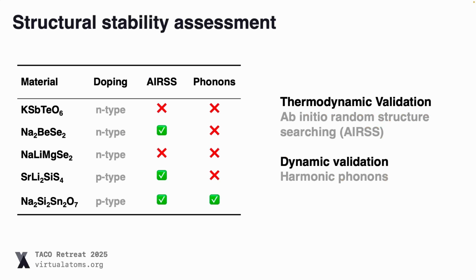So we wanted to understand finally whether these materials that have been proposed were actually stable. And so what we did is we essentially did ab initio random structure searching from scratch to see whether we would get the same structure that the GNoME paper had proposed for that composition. So ab initio random structure searching is a global optimization search, which is unbiased. It's quite expensive and inefficient, but it does often work and find you the actual ground state.